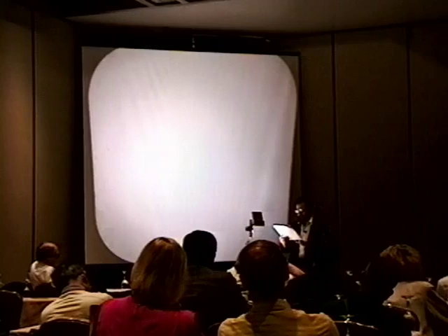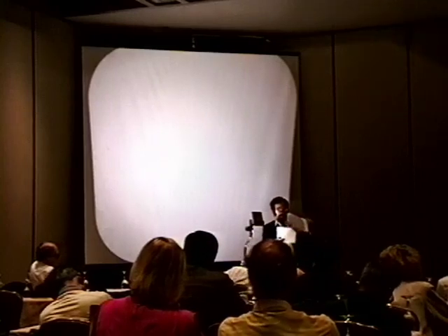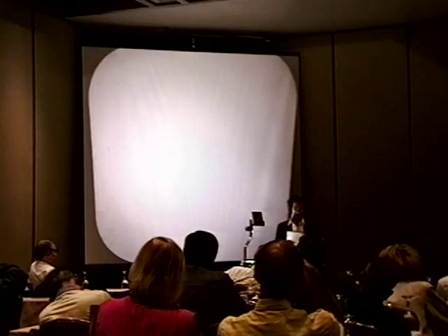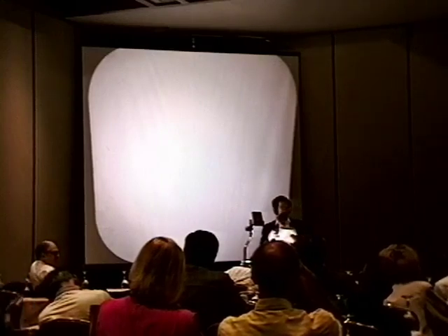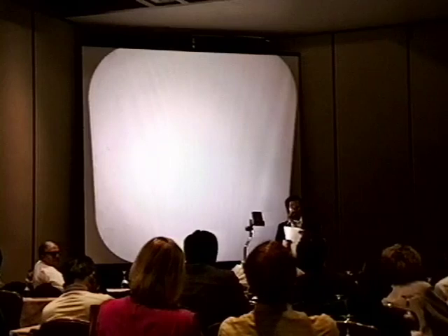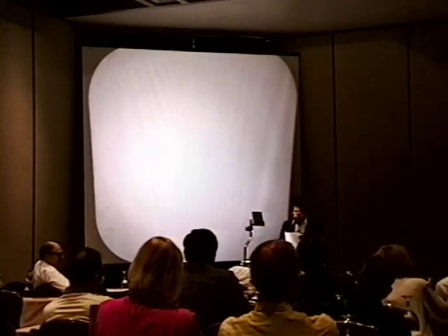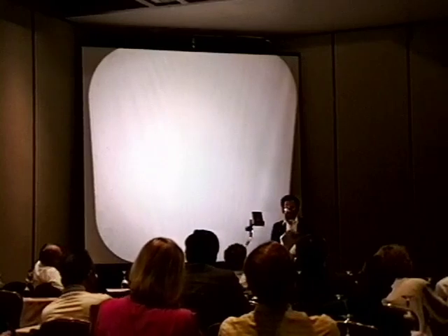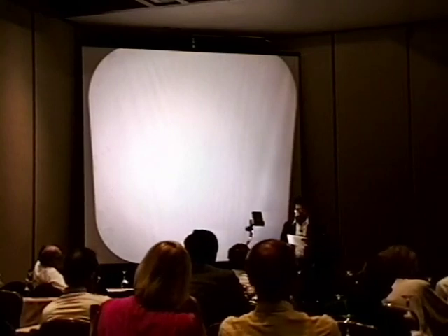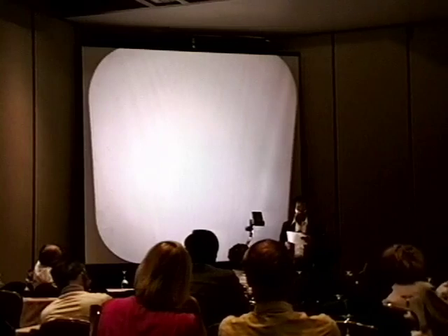Ordinarily, a cavity in liquid is unstable, but it can be stabilized by the alternating cycles of compression and expansion that an acoustic field produces, provided the sonic amplitudes and frequencies are properly chosen. The study of coherent SL, now underway at UCLA under the direction of Professor Seth Putterman, has yielded some remarkable results. What to the naked eye appears as a steady, dim blue light, a photomultiplier reveals to be a clock-like sequence of pulses in step with the sonic period, which is of the order of 10 to the minus 4th seconds. Each pulse contains about 10 to the 5th photons, which are emitted in less than 50 picoseconds. That is about 10 to the minus 11 seconds.